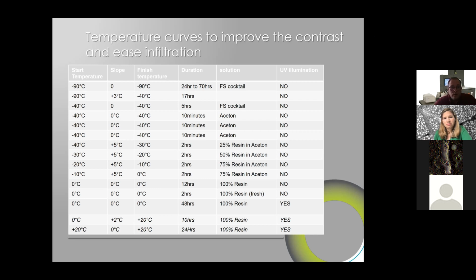Another thing which is annoying to all of you is the fact that the resin is not that fluid at -30 degrees. It's quite viscous. So what I did was to try to embed at 0 degrees Celsius. So basically the 100%, which is the most viscous part, at 0 degrees Celsius, and it works fine. And the embedding is quite good. So I'm also looking into raising the temperature more progressively along with the embedding step with the resin, up to reaching 0 degrees Celsius with 100% resin, so that the embedding will be better, infiltration would be easier, and the handling of the resin on its own will be as good as Lowicryl, hoping that we will preserve the ultrastructure and have a better embedding. So this is also in the pipeline.